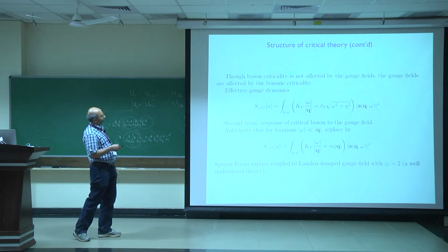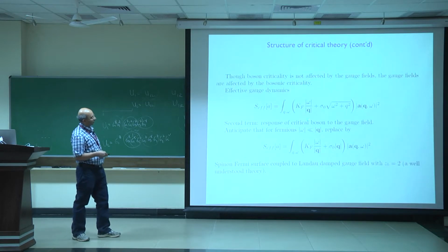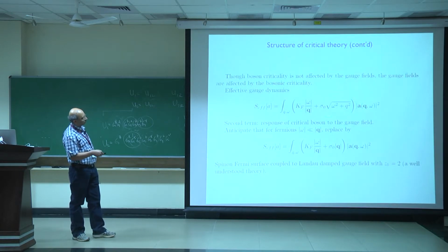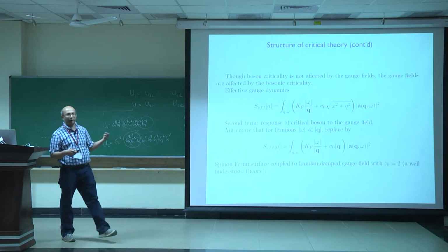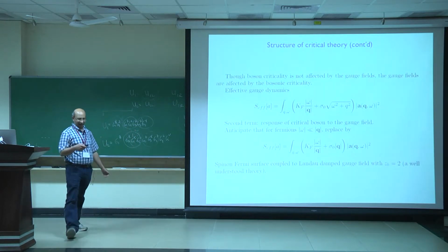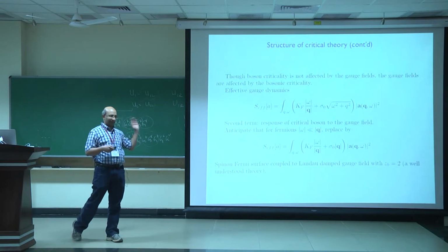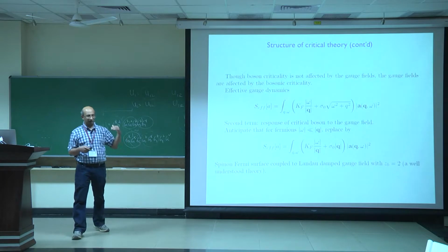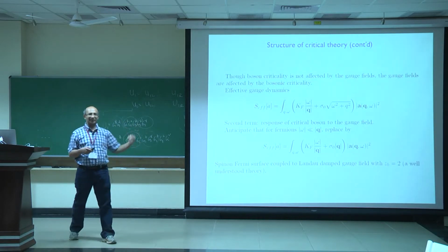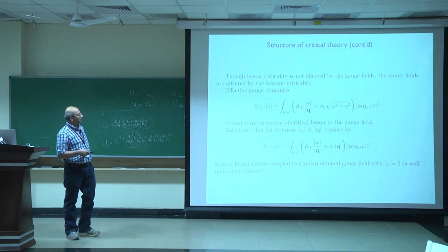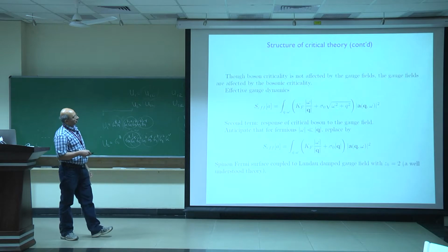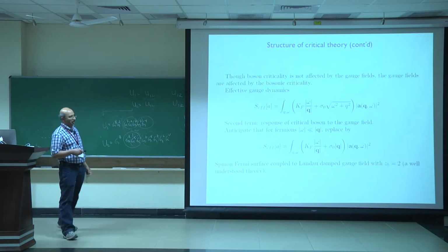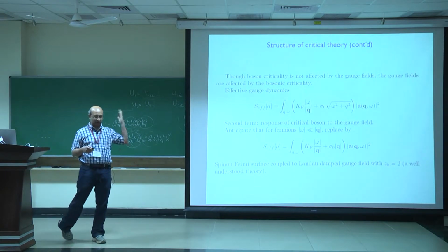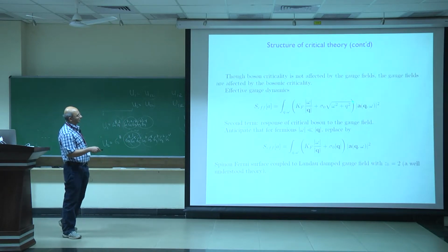And the reason is the following. The effective gauge dynamics, so this term, this Landau damping, comes from the Fermi surface fluctuations, while the critical boson fluctuations lead to a term in the gauge dynamics which looks like this. This is the standard response of a relativistic quantum critical fixed point to an external gauge field, and it merely reflects, if you wish, the fact that a 2 + 1 dimensional superfluid insulator transition of bosons is characterized by a universal conductivity that's of order 1 at the critical point. Or equivalently, or more formally, you can say that it's fixed by the scaling dimension of the vector potential at this CFT, and the scaling dimension is fixed to be 1, and therefore scaling determines the structure.